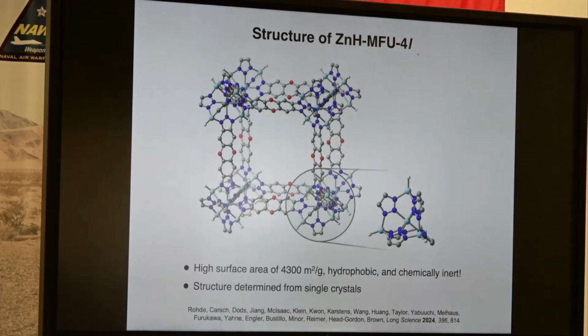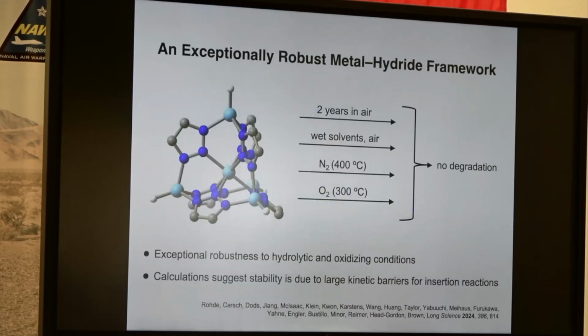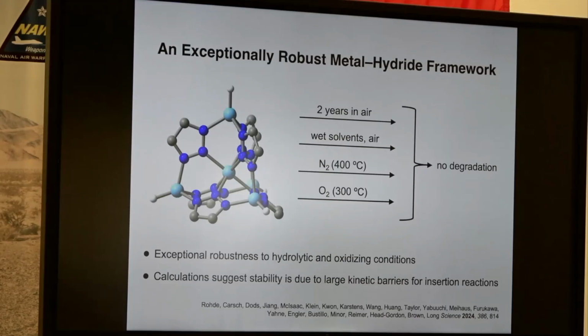And if you make this in the hydride form, it has, again, very high surface area. It's incredibly unusual in that it's a metal hydride that you can put on your bench top, and it doesn't react with water or oxygen. So for those of you who are chemists working with metal hydrides, a lot of them are very sensitive. A lot of the ones you use in your reactions, you don't bring out onto your bench top. But this you can sit on your bench top for 2 years, and there's no loss of the hydride, no degradation.